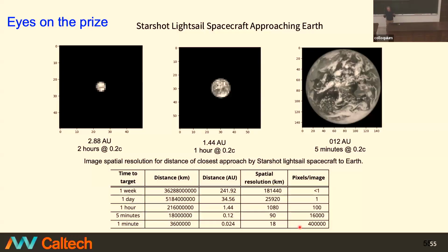It has to do with just diffraction limited optics. I have an optical aperture on the Earth, this phased array laser. That is the farthest distance I can go and maintain a diffraction limited beam spot that doesn't overfill the light sail. When it starts to overfill the light sail, the propulsion efficiency falls off, right? Because a lot of optical power, the full width half max of the beam, is now larger than the light sail itself. So that's really the consideration.